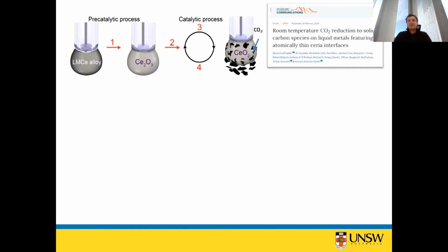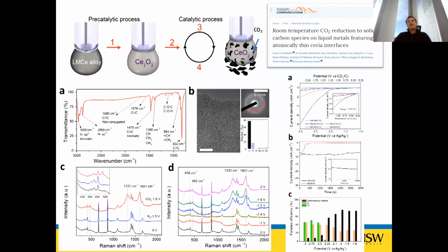But the fascinating thing is CO2 breaks down, produces these C-C bonds on the surface, it produces flakes of C on the surface. And the onset voltage to produce is very, very low. It's only 310 millivolts. So the total energy needed is very, very low. And the conversion efficiency, the Faradaic efficiency, is very high. At minus 1.8 volts it is almost 80%. And it keeps continuing happening.